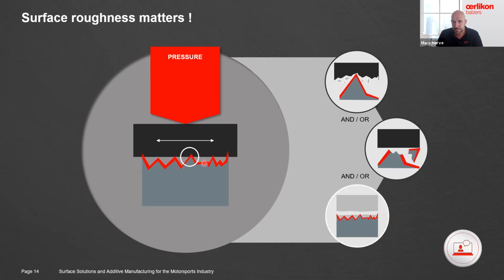Or a third possibility is that the counterpart is so soft that you make a transfer of this soft material to the coated part, and suddenly you're back to an uncoated surface. So you don't have any benefit from the coating. Again, a quick reminder: the coating is one thing, but the way you prepare the component before the coating makes a big difference at the end for the use inside the engine, for example, if we talk about motorsports applications. Okay.